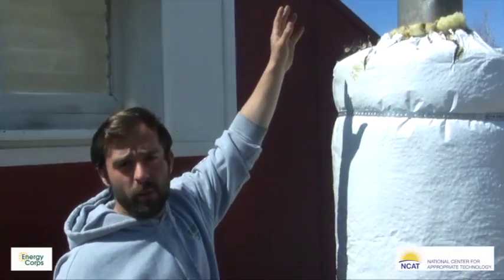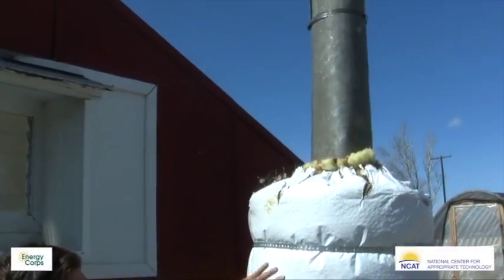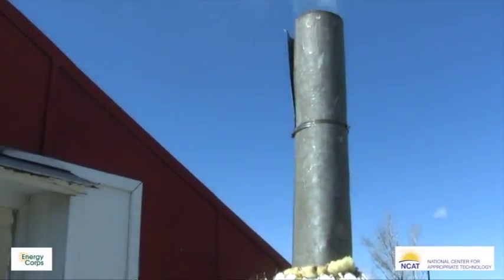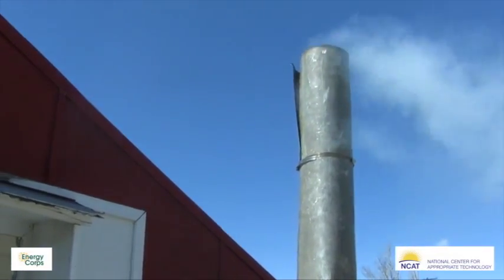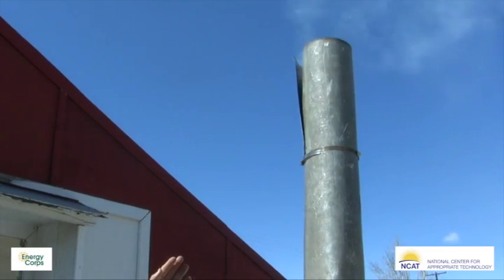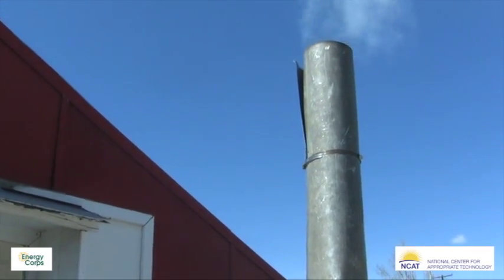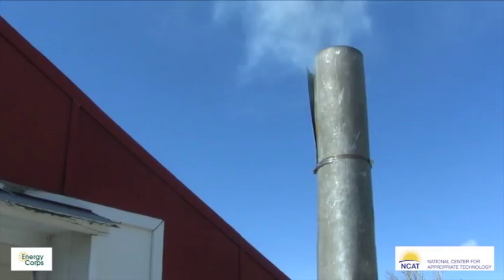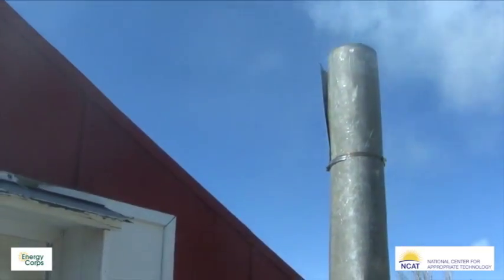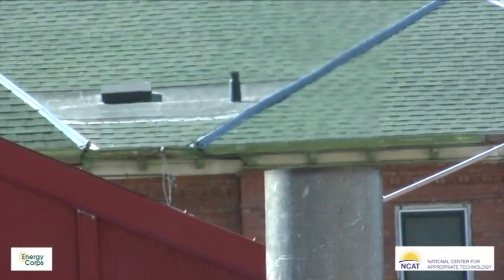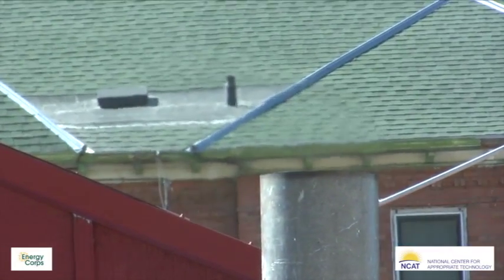So one good thing about rocket mass heaters and rocket stoves is they're supposed to burn very clean, but in our case you might get a little bit of smoke at the top, and that's because it hasn't got hot enough inside this chamber yet to flare off those wood gases. So you will see a little bit of this, but once it gets hot enough, those wood gases should flare off inside the chamber, and you should see very minimal smoke out of the top of the stack.